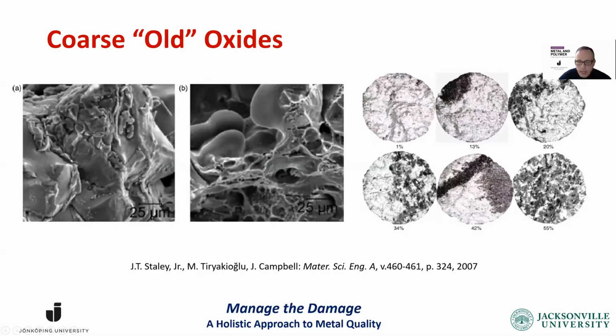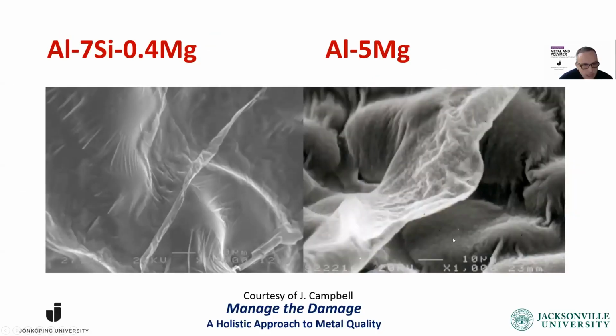Now, obviously, this is not just pure aluminum or aluminum alloy. It has a lot of alumina in it because of the surface entrainment. And there are young bifilms that are only maybe nanometers thick. They form in a very short period of time, perhaps when the air bubble is rising or when you're pouring the metal, as we usually do. These form instantaneously, and they get entrained into the body of the casting.